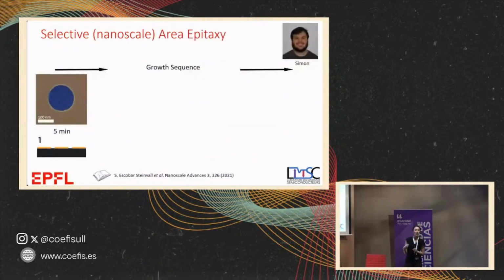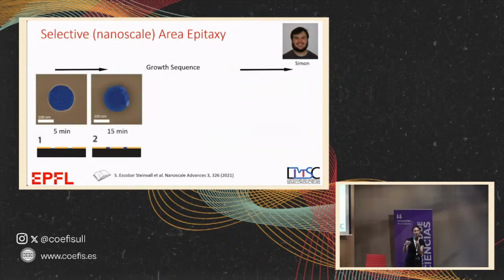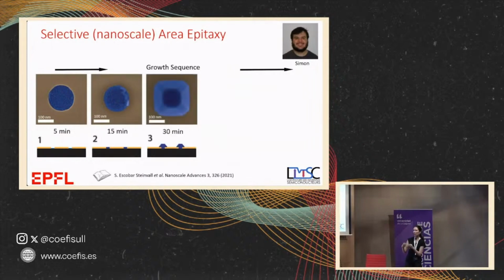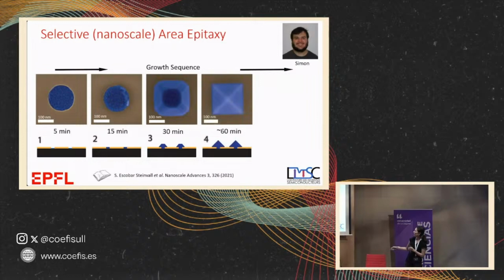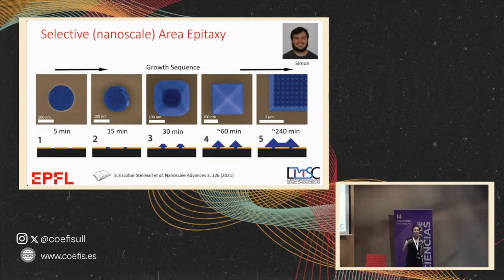So the other approach, which is much better, is the nanoscale approach. You start making, again, a mask where the atoms don't stick, and you start growing inside. And then you let the material create. The strain dissipates, and then it starts creating what it wants, so these facets and a pyramid. And then if the pyramids are close together, you will create a thin film that is structured like this. And so you use the nanoscale to nucleate. It dissipates the strain, and then you create a thin film with very few defects.